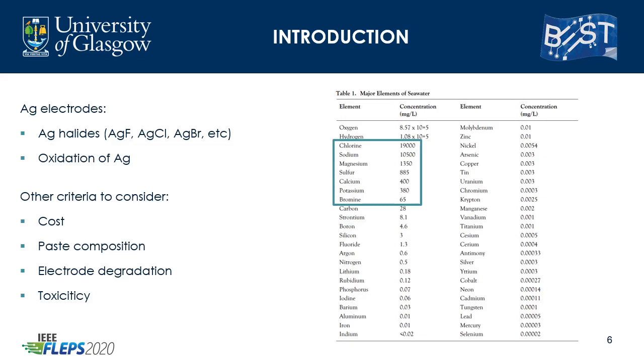There are, however, many other criteria to consider, such as paste cost and composition, electrode degradation, toxicity, and so on. In this context, it seems carbon could be considered as a more suitable low-cost option. But commercial carbon inks tend to have a higher resistance, which can hinder some experiments. Therefore, some compromises might need to be taken. In this paper, we wanted to focus on all silver and all carbon electrodes, as it's important to understand how the choice of electrode material can affect the experiments, ranging from their electrical resistance to electrochemical properties.